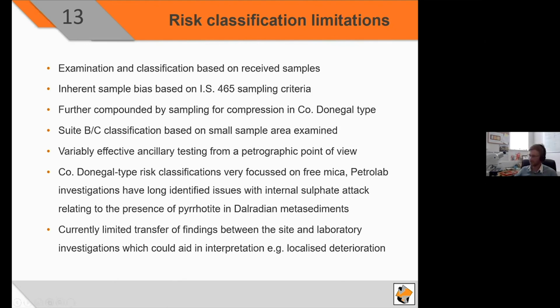The County Donegal type risk assessment is very focused on free mica. Petrographic investigations have long identified issues with internal sulfate attack relating to the presence of pyrrhotite within the Dalradian sediments. The high presence of pyrrhotite, in the absence of free mica, does not necessarily mean that blocks within County Donegal or County Donegal free mica type investigations will provide high classifications, where in reality, if they are considered along the lines of the sulfide risk assessment based on the pyrite testing, these would provide high classifications. There is also a certain limitation between the site and laboratory findings, which could aid in interpretation, i.e. specific localized investigations of deterioration, which could give us better indications of how this material is faring in situ.